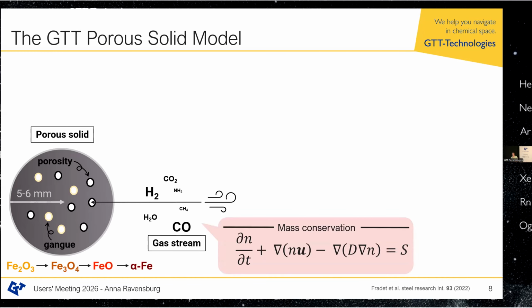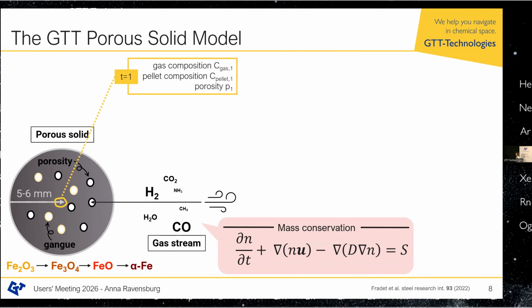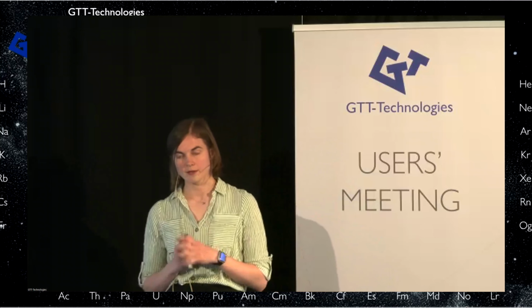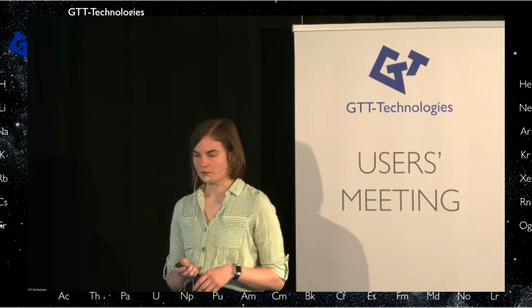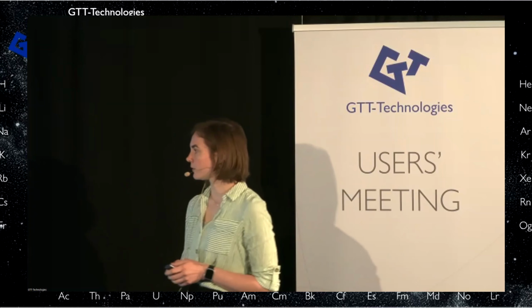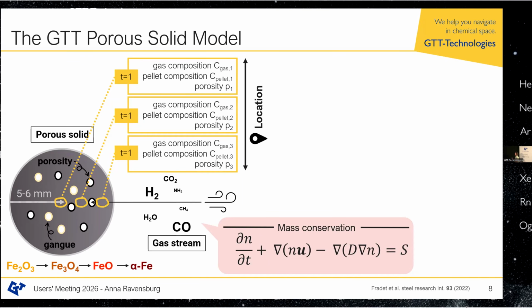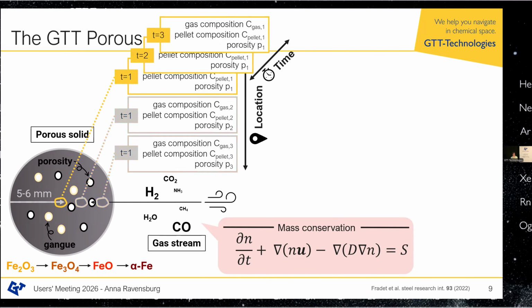You just apply the energy and mass conservation to it, and discretize this equation in space. So at every point and location, here at the core of the pellet, you have a certain gas composition, a certain pellet composition, and a certain porosity. And then you also have this if you move out in the radius, and then you discretize it at these different locations, and you don't only do this in space, but also in time. And with this, you can solve this energy and mass conservation. We also take into account the driving force, which is also something that Moritz pointed out is quite important. And with this, we have tried to come up with this porous solid model.